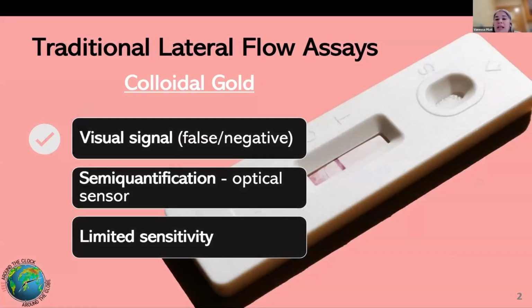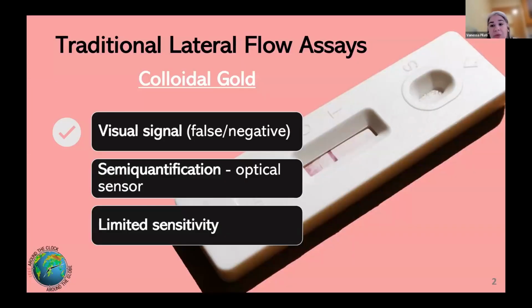Most of the commercial lateral flow assays are based on colloidal gold nanoparticles and microparticles. They provide a visual signal, usually a red line that we can see in the test line or in the control line. Sometimes we want to know the concentration of the analyte in the sample, which is the biomarker we want to detect. This is very challenging because it is an optical-based signal, with variations in ambient light and modifications in the color of the paper. This is very difficult to achieve. So we have just a semi-quantification of the biomarker in this kind of lateral flow assays, with a lack of sensitivity.